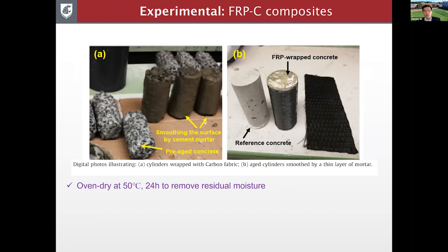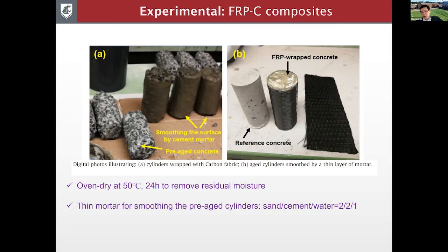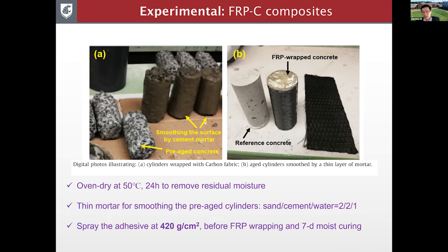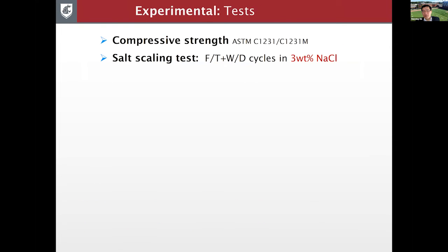And for wrapping the FRP to the concrete cylinders, this is dealing with 2 different groups, right? One is the new or reference one, the new concrete or the pre-aged ones. So for both groups, we start oven drying them to remove residual moisture. And then for the pre-aged one, sometimes you have significant scaling due to that salt scaling exposure. So we had to smooth some of the surface with a very low quality mortar, I would say, water cement ratio of 0.5, just so that your FRP would bond better. And then spray this adhesive at this dosage recommended by the vendor before wrapping the FRP and cure it for 7 days.